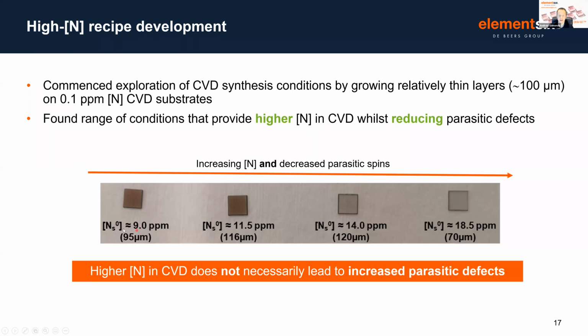We can see that actually as we move from left to right, our nitrogen concentration in the material goes up, but clearly the amount of discoloration of the sample, which we're using as a proxy to the content of parasitic, potentially paramagnetic defects, this goes down. So we produced a high nitrogen containing material that has a lower concentration of parasitic defects. This is exactly what we want and what we were after in terms of developing this sort of diamond material. So really the message here is that high nitrogen CVD doesn't necessarily lead to an increased level of parasitic defects. We can control that.